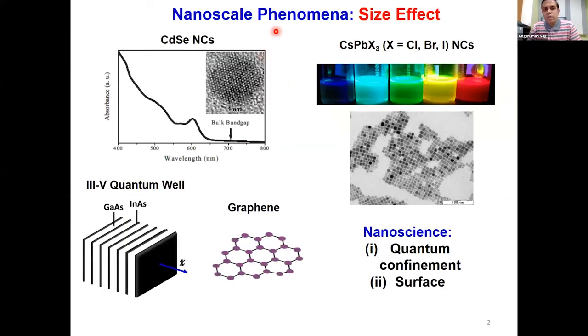So when we talk about nanoscale phenomena, we have seen in the previous slides very excellent interfaces that were shown by Professor Paul Weiss. And others, kind of nanoscale phenomena, often we refer to the size effect. For example, I have taken this data from my PhD thesis. So these are cadmium selenide nanocrystals, about 5 nanometer in size. And optical data shows that there is an increase in band gap compared to the bulk cadmium selenide, which is the classic case of quantum confinement effect in semiconductor nanocrystals.